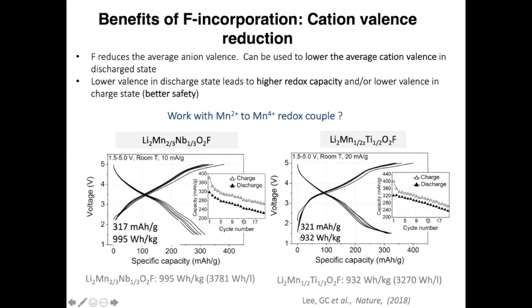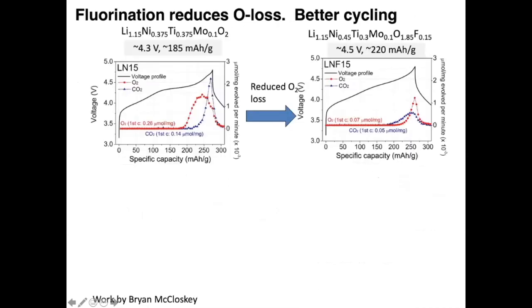But what's really important here, the valence state of manganese is still only 4+ in the charge state. And that's a quite stable valence state for manganese, unlike say nickel 4+, which leads to a lot of oxygen release. So this is an important role of fluorine. The other thing it does is it reduces oxygen loss. As you know, almost all cathode materials at the top of charge in the first few cycles lose some oxygen. That's true for NMCs, that's true for some DRX materials.